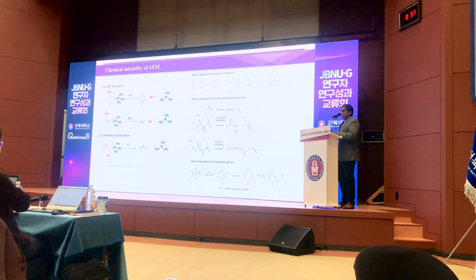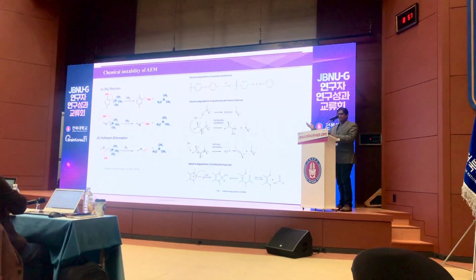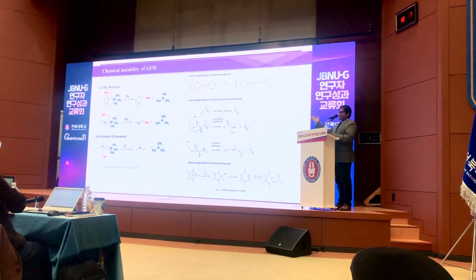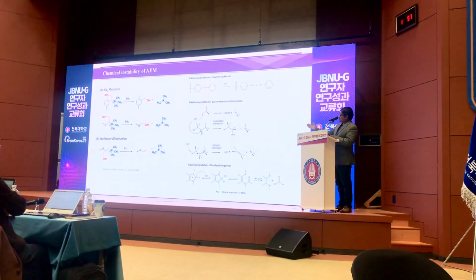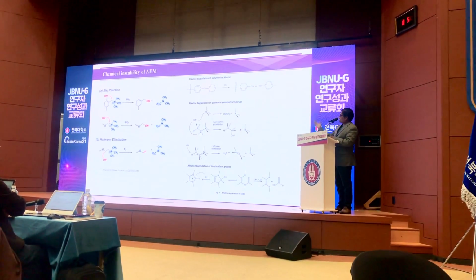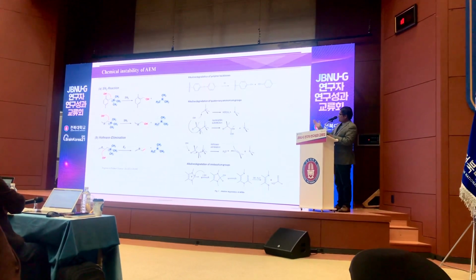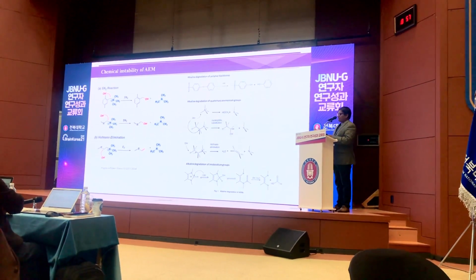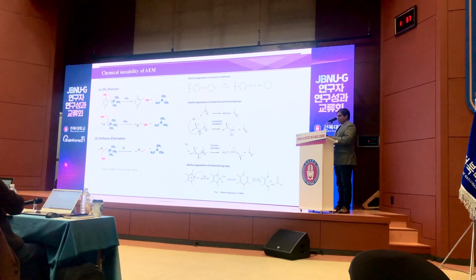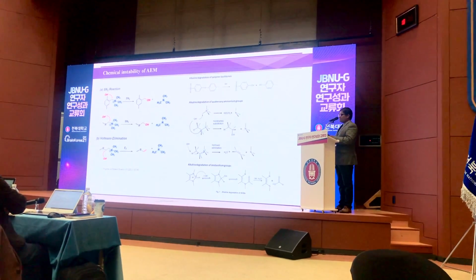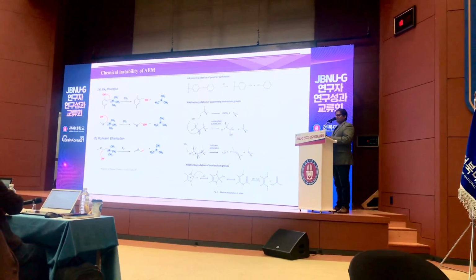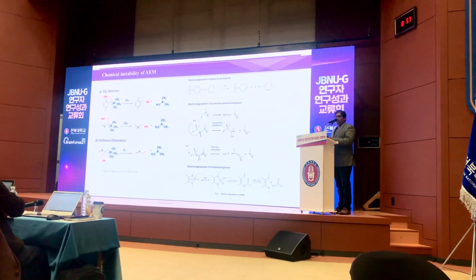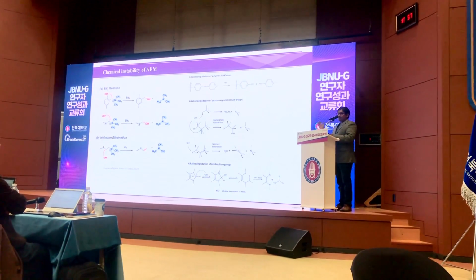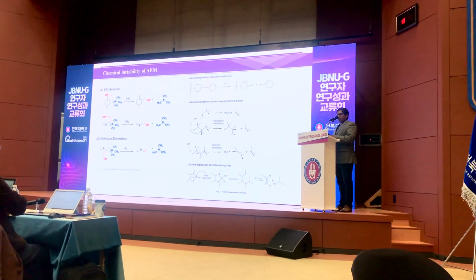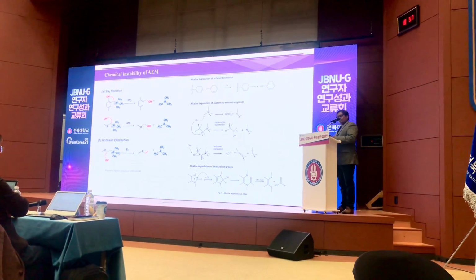Even though anion exchange membranes have advantages over proton exchange membranes, there are still problems, as they can easily degrade by the alkaline OH minus, as shown here. Different mechanisms have been proposed, that is SN2 reaction, Hofmann elimination, and E2 elimination. So by having all these mechanisms, the membrane can easily degrade. As researchers, we need to avoid all these problems. That is how we design the electrolyte, which will then be used in the fuel